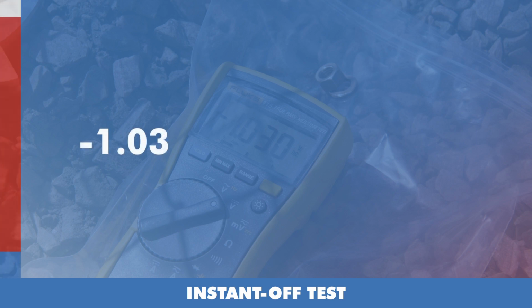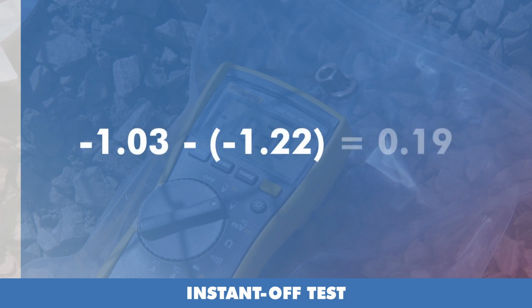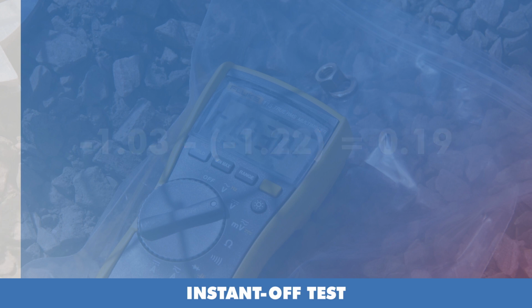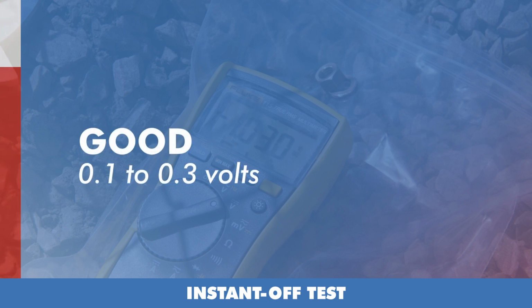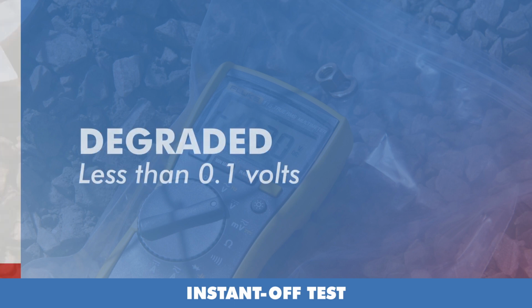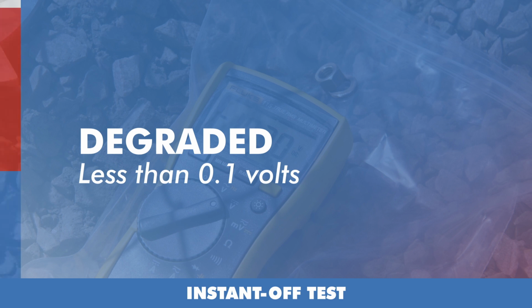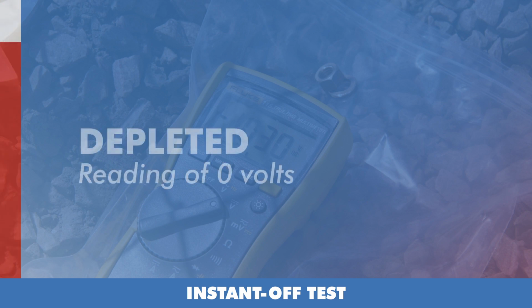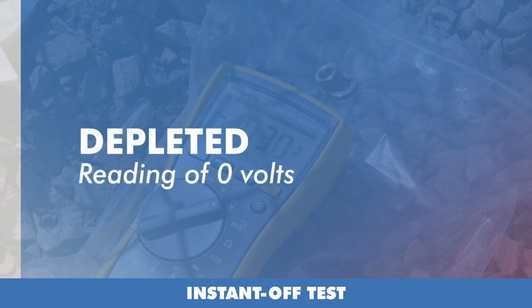Then subtract the voltmeter reading of the system performance test from the instant off test reading. The difference of the two recordings should fall between 0.1 and 0.3 volts. The higher the better. A difference of less than 0.1 volts indicates that the anodes are degraded, but protection is still adequate, but plans should be made to replace them. A reading of 0 means that the anodes are depleted and immediate replacement is required. The anchor shafts are no longer being protected.